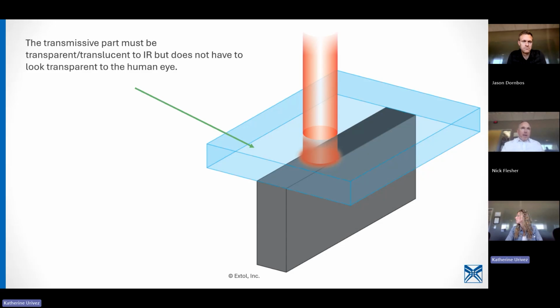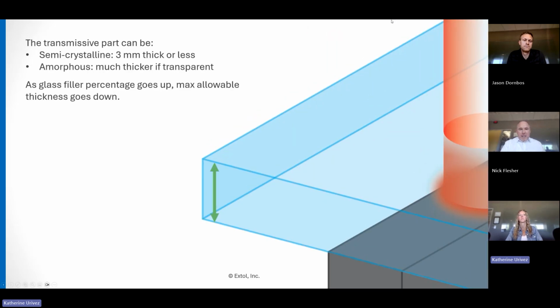The most common example that we give, and we didn't provide these systems, but most everyone is familiar with Apple's AirPods. Those are laser plastic welding. White on white is kind of the most challenging application because they can discolor, but that's just an example of challenging your norm of, well, it has to be clear or black. Not necessarily. A transmissive part, semi-crystalline, we just roughly say 3 millimeters thick or less. I talked about fillers. If you're using talc or glass, we really suggest 3 millimeters or less if you can, especially if you need a strong part.